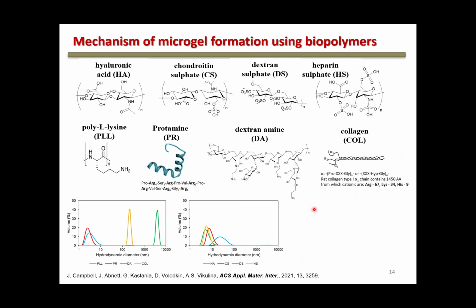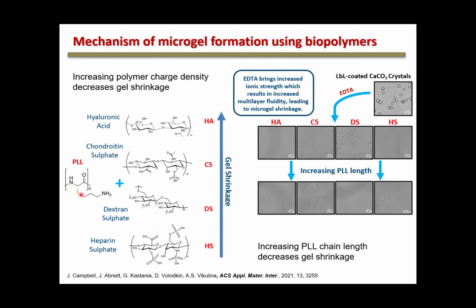So, and to better understand the mechanism from a fundamental point of view, we have tested in our previous publication a couple of years ago 4 different polyanions and 4 different polycations. So I won't go much into details, but it was 16 different combinations of well-defined polymers when we tried to understand what's happening. And we found out that, again, for the same one of them can be used polylysine as polycation, and the range of 4 different polyanions with the charge density increasing from top to down. You can see it from the schematics. If you go from top to down, there are more and more charge groups on the polymer backbone. This is a disaccharide unit.